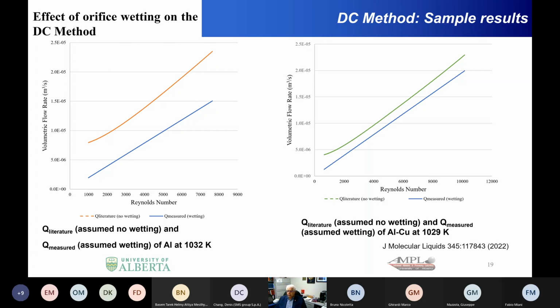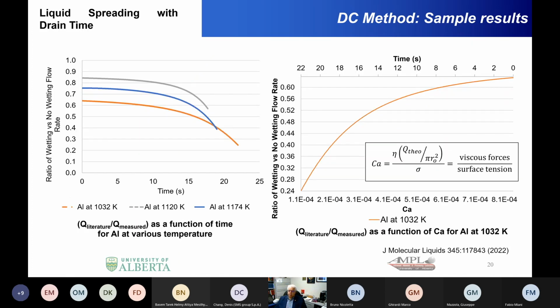And so here we see that the choice of material you use, and whether it results in wetting, can dramatically affect the results that you get. And it will affect the parameters that you get at the end in terms of density, but it turned out that the viscosity and the surface tension were still quite acceptable.